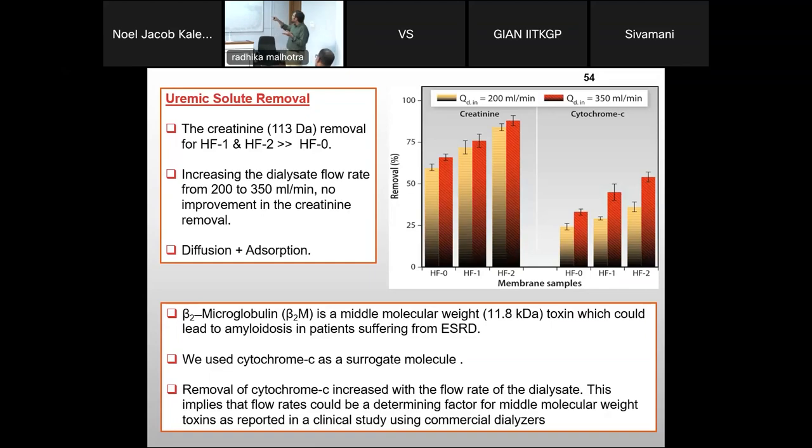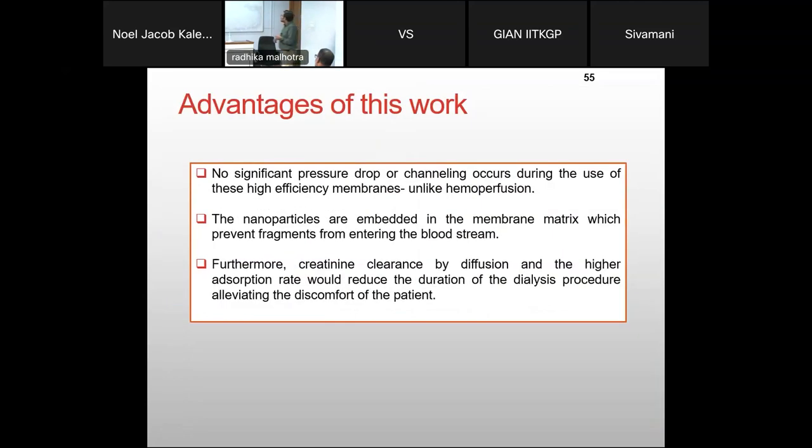so the yellow colored lines mark 200, and it is always slightly higher when it's run at a higher flow rate, or when the dialysis side flow rate is higher. So for both creatinine as well as cytochrome C. So the advantage of this work was there was no significant pressure drop or channeling when using these high efficiency membranes, unlike hemoperfusion. So these membranes, I said they had an advantage, or they could adsorb creatinine even in static